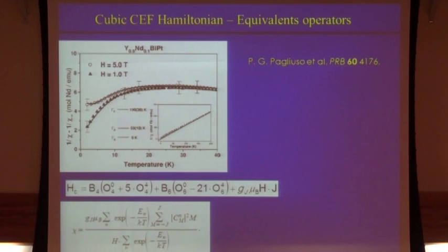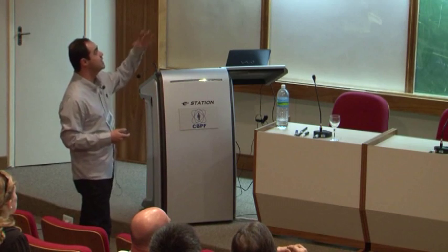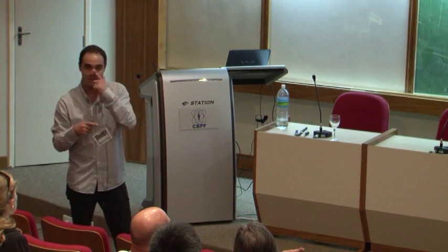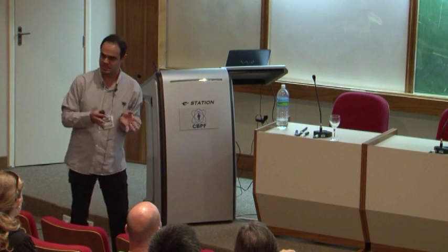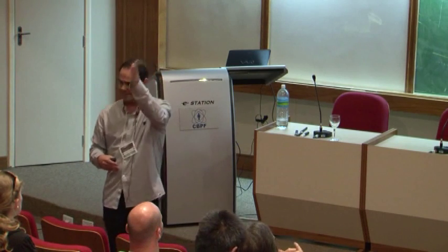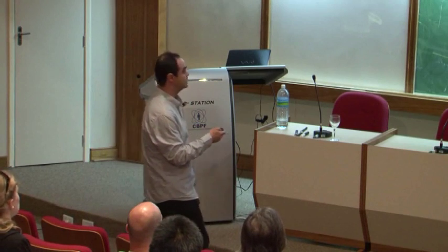Using different crystal field schemes and get the scheme that will give you that departure. So that's very complicated to do only by magnetic susceptibility because you can have different sets of parameters for your fitting. But you can usually change your rare earth, make it consistent, fit, and try to relate many different properties that will be affected by the same scheme to be sure that we're doing something right. Or you can go and try to measure directly by inelastic neutron scattering, for instance. But sometimes you don't need to do that because you can get it from your own measurements.